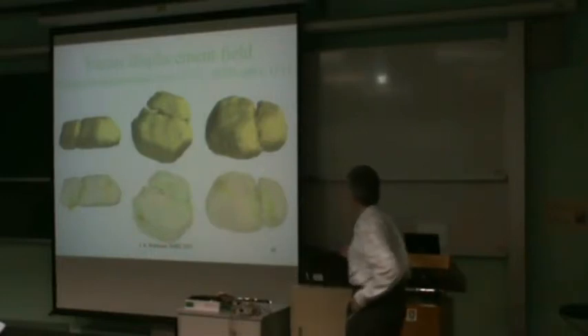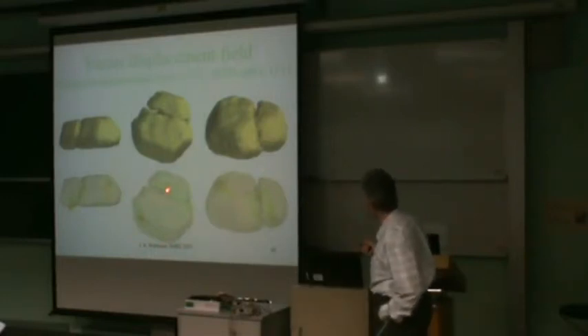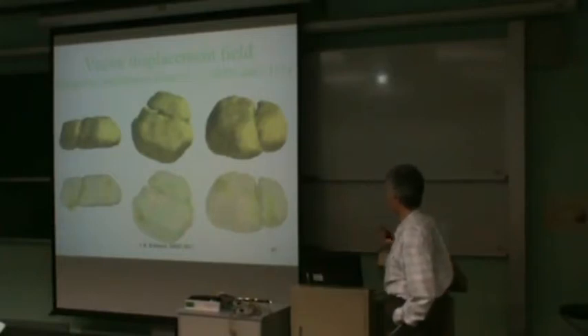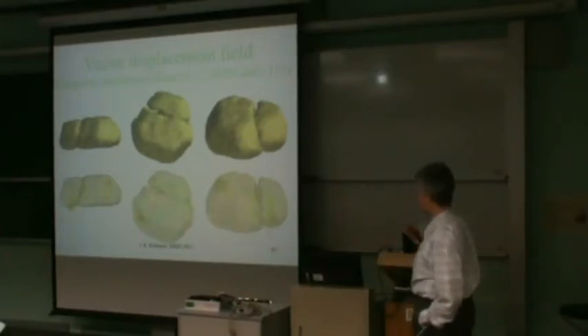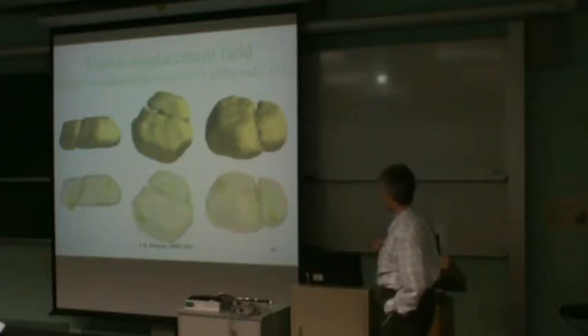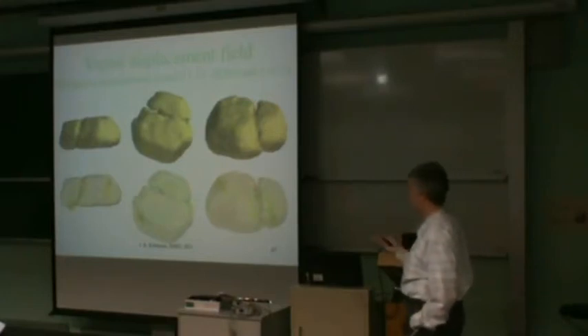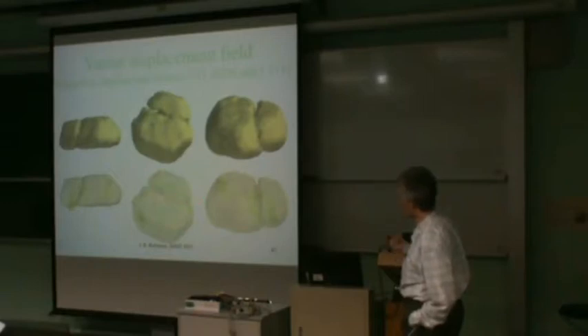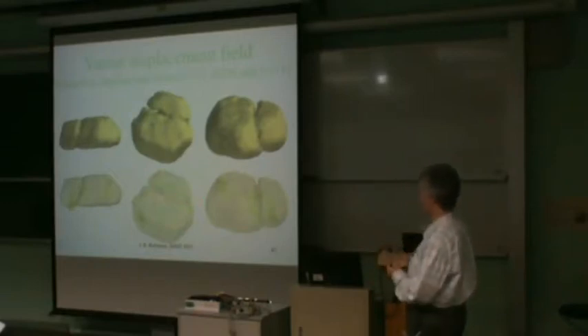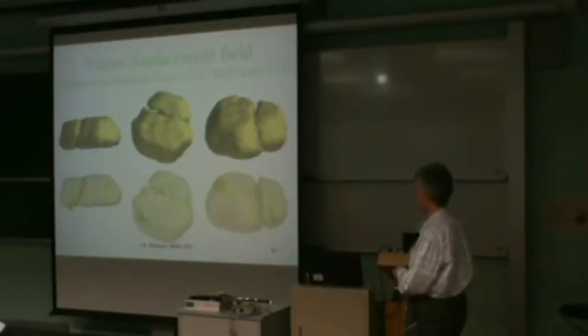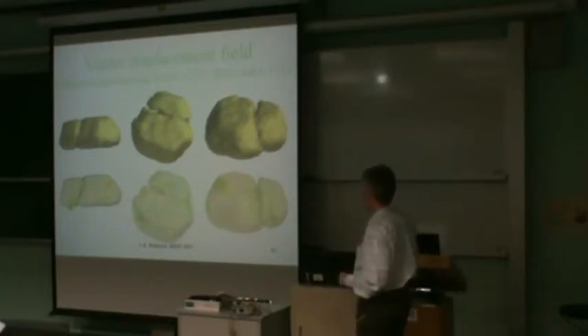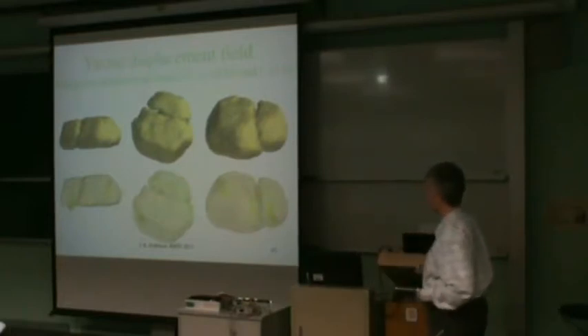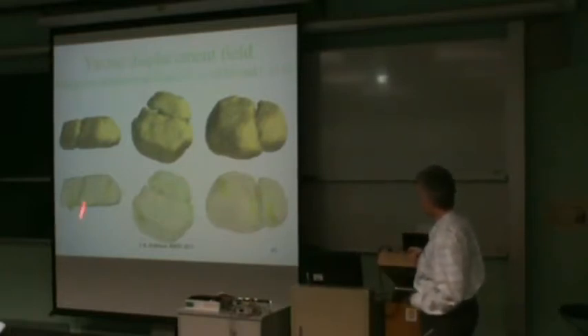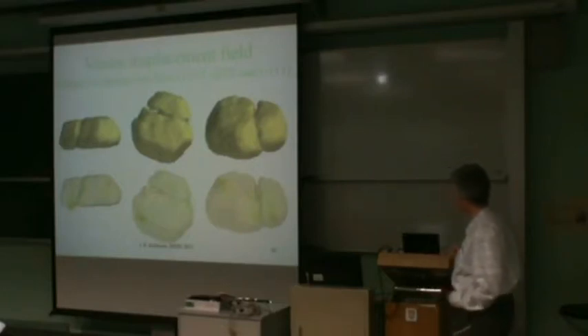So if you look carefully, you can see on the bottom image here, this is the one where he's measured, I think, I don't remember exactly how many Bragg peaks, but let's say 3 Bragg peaks from the same crystal, which allows you to get 3 different components of the displacement field. And if you look carefully, you can see the displacements tend to line the region next to the stacking fault. So there is a strain associated with that stacking, that missing piece of material associated with the 2 stacking faults that lead to this gap in the shape of the crystal.